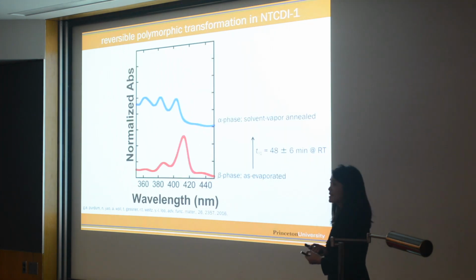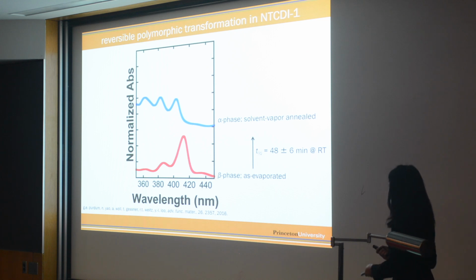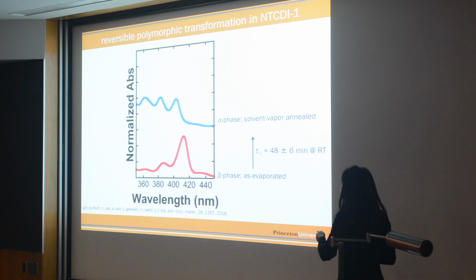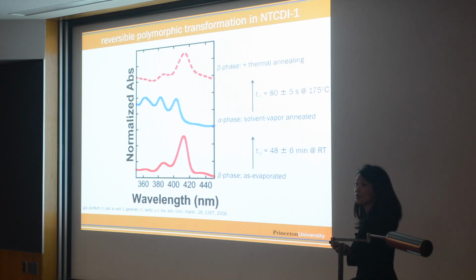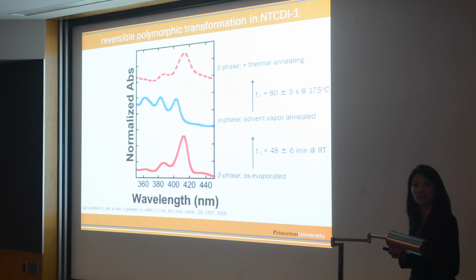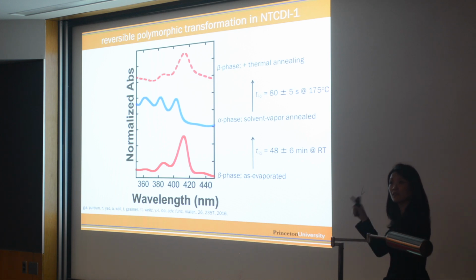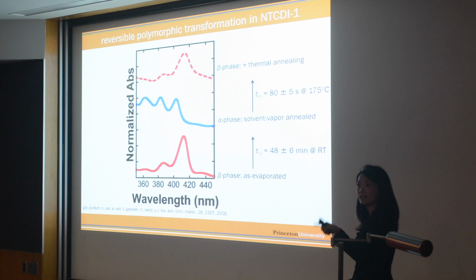So let me summarize what we see in NT-CDI1. As evaporated, we access the beta phase. We can solvent vapor anneal, and we access the alpha phase. And if we take the alpha phase and thermally anneal, we get back the beta phase. So it appears that these polymorphs are reversible, and we can go round and round.